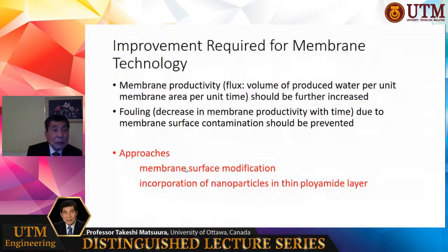There are two requirements. The first one, membrane productivity has to be increased. Productivity means what? It is expressed by flux, volume of produced water per unit membrane area per unit time. If this flux increases, then you can reduce the size of the membrane, and therefore productivity is increased quite a lot. So flux increase is very important. And another thing is fouling. It is a decrease in membrane productivity with time due to membrane surface contamination. This should be prevented. So these are the two problems to be solved.